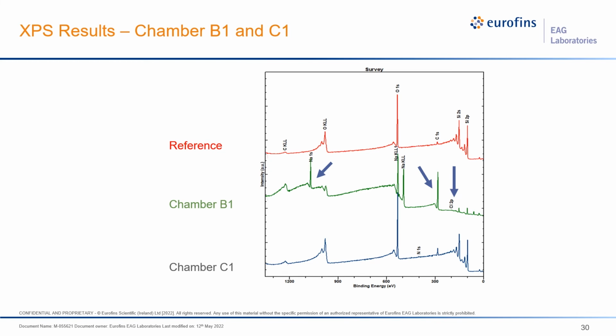In chamber C1, we see this little nitrogen peak here that popped up that might be the amines that the FTIR had been looking at. Other than that, it looks fairly similar to the reference chamber, so it looks fairly clean except for the nitrogen peak.